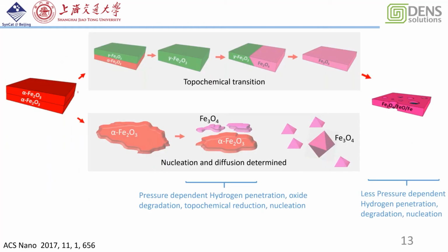Here, based on the references and my work, I proposed that the reduction of the iron oxide to finally metallic iron proceeds in different steps. The middle step is influenced by pressure. We can see that with high pressure and with low pressure, the phase transformation is very different. They proceed in two steps. They call the first the topochemical transition step, from the iron oxide to the magnetite. With high pressure, this is generally dominated by nucleation and diffusion. And afterwards, the last step from the magnetite to metallic iron is less influenced by pressure. This is very strongly controlled by the kinetics, and the production of the metallic iron generally comes from the nucleation process.